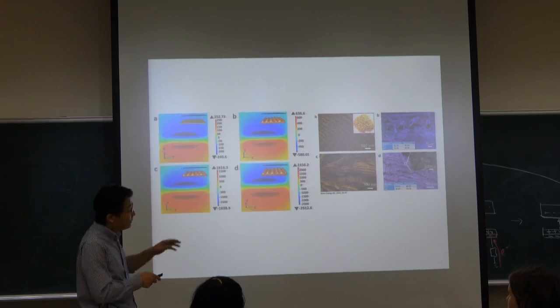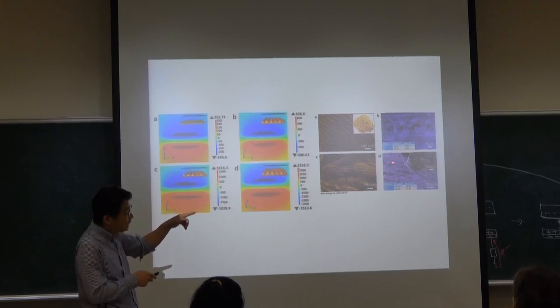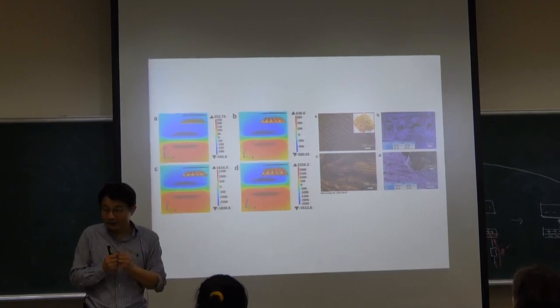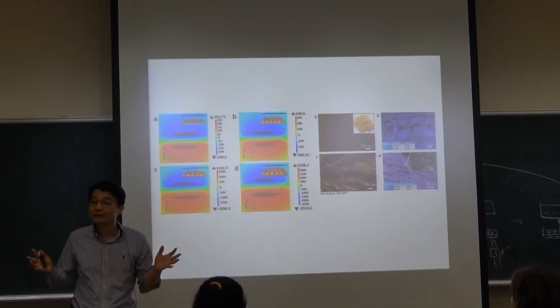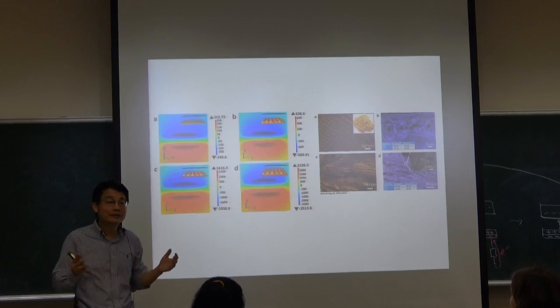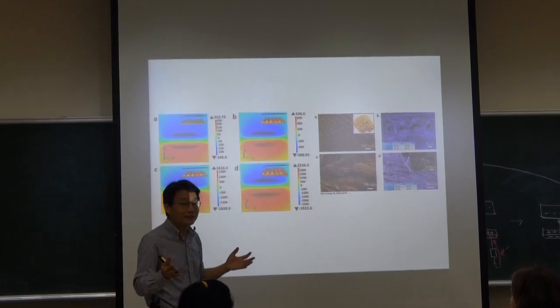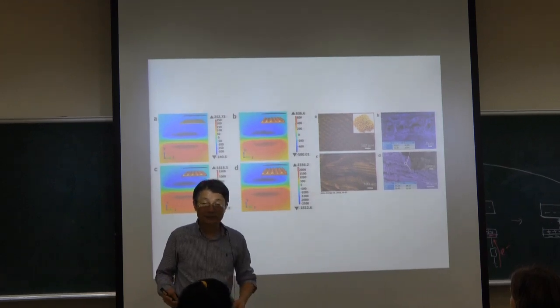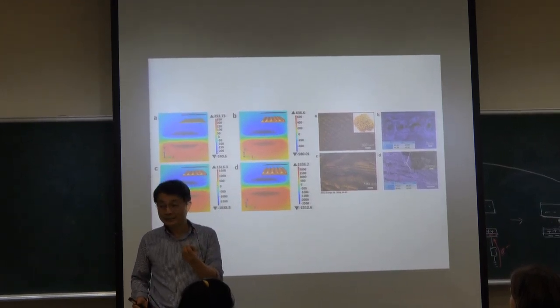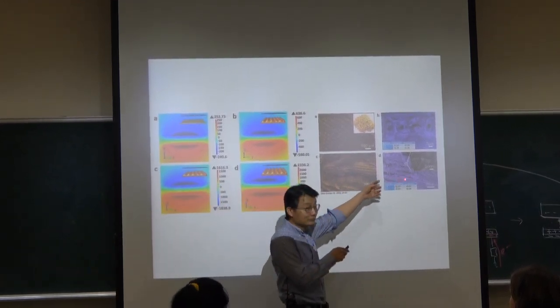Finally, after releasing the cellulose, you can increase the temperature. The cellulose will be burned out. That means the CNF will be burned out. Once the CNF is burned out, finally what remains is porous SiO2.